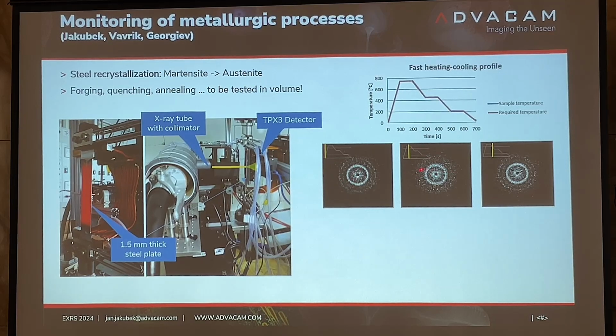And during the heating, at the beginning we saw such a pattern behind. Then the pattern changed. If you are careful enough, you would see that these secondary rings are not there. They are kind of blurred. And then if you cool it back, it appears again.